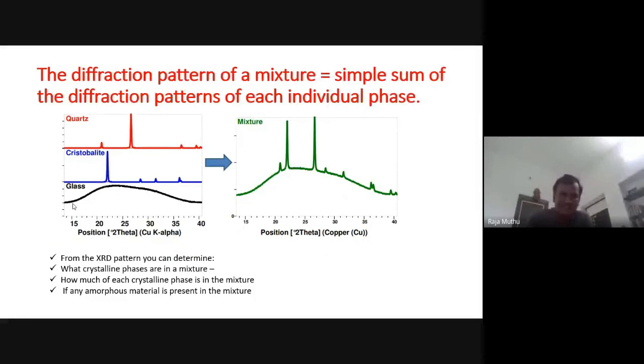Now, the diffraction pattern of the mixture. If you take these three, a mixture containing quartz, cristobalite, and glass, then the resultant XRD will come like this. So this will be the resultant if it has a mixture of these three. From this, we can understand that it has an amorphous phase, and of course it has a crystalline structure also. From the XRD pattern, we can determine what crystalline phases are in a mixture, how much of each crystalline phase is in the mixture, and whether any amorphous material is present. These things can be studied.